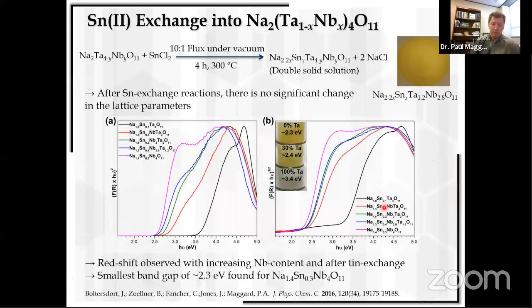Okay, and so we've looked at this for many of our materials, and in recent years we've been moving away from copper because of its stability problems, and shifted more towards tin-containing systems that also result in very small band gaps. But they're very difficult to make because tin 2+ is an unstable oxidation state. It oxidizes easily, it decomposes easily, and it's very hard to make. But luckily, all we have to do is put in enough tin to surpass that percolation threshold and get the favorable electron hole separation to drive these photocatalytic reactions.